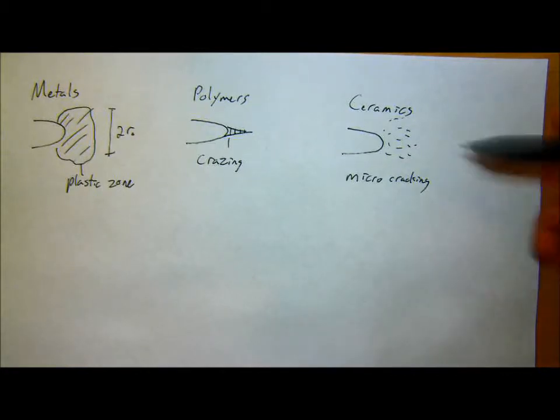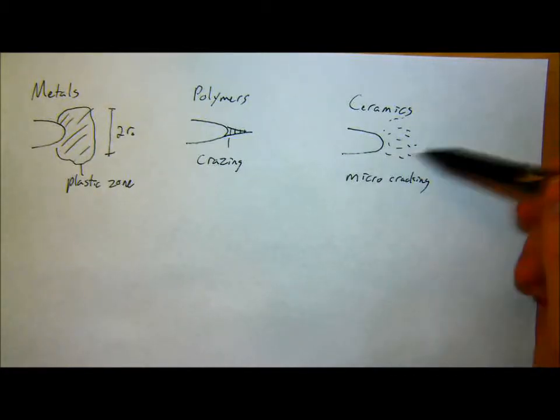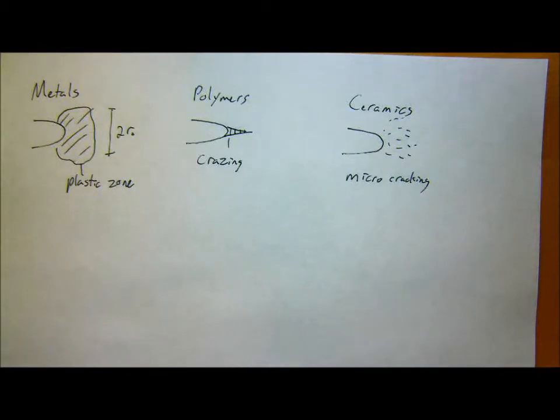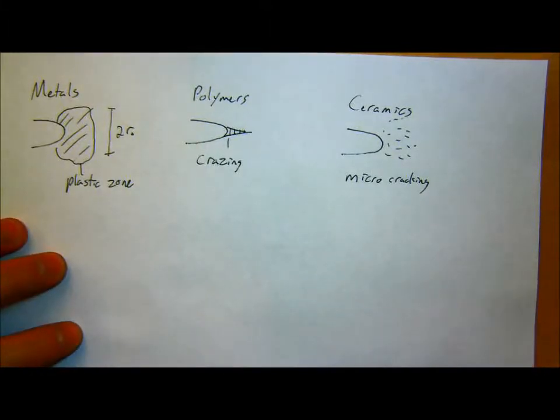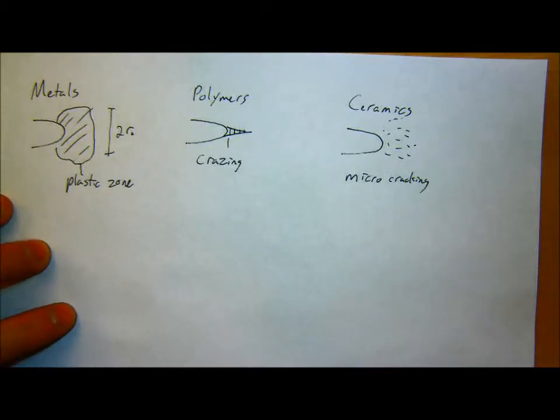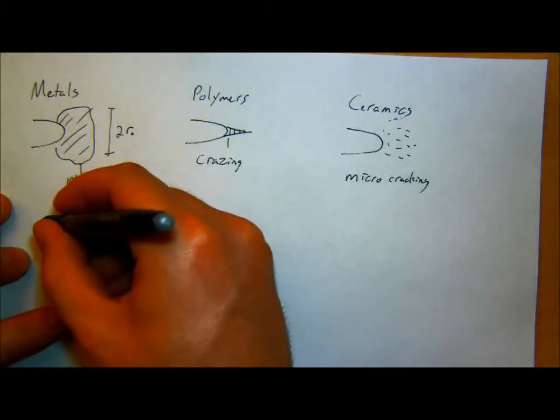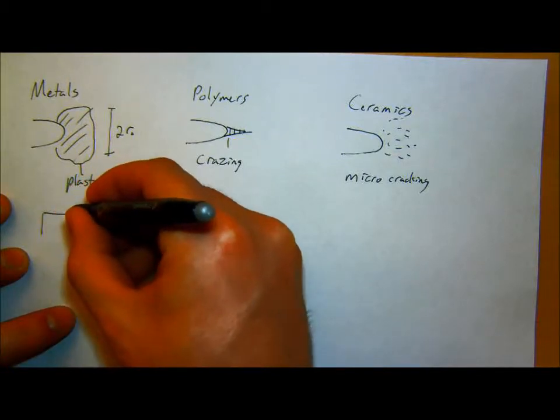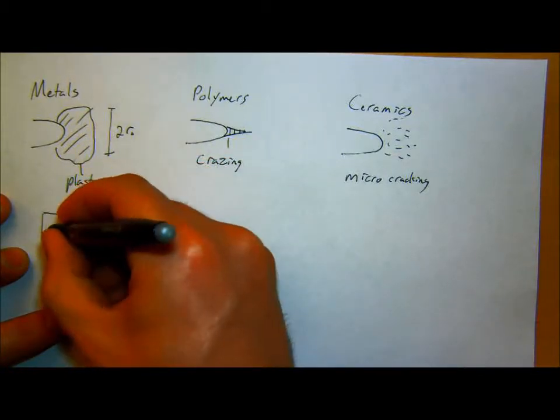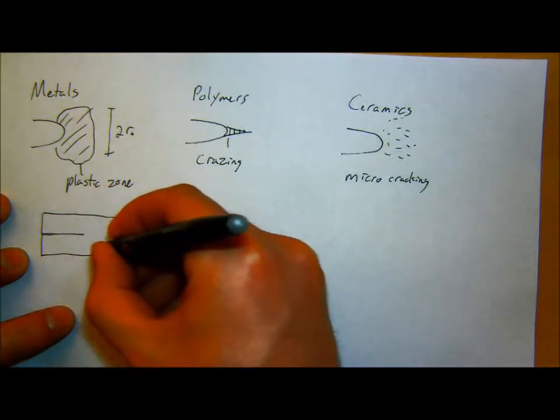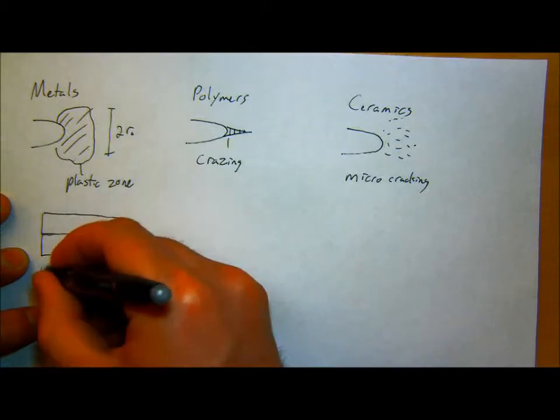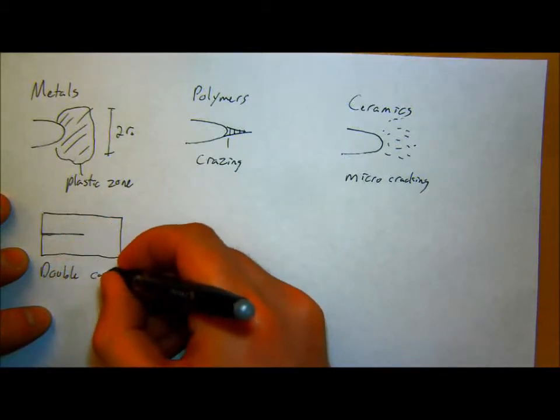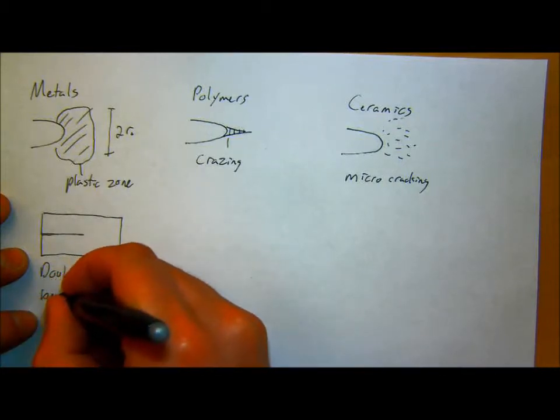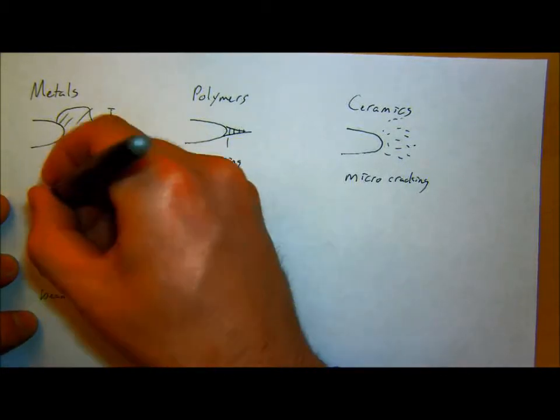So there's a few different ways you can go about testing these things. One of the most common, there's a couple that are fairly common. There's a double cantilever beam where you bring a long crack into a material. Cantilever beam, where you then apply some force to a part that's basically glued together. So this is very common for something like composites, where you have lamina glued together. You pull those two lamina apart and you look at how it cracks. There's a compact tension specimen.